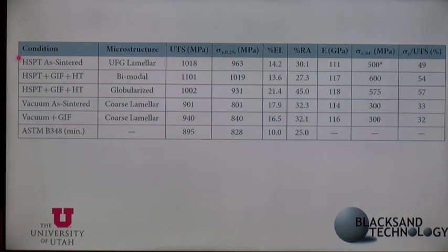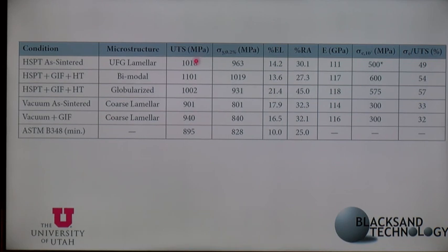Here's a table just showing generally what these things go through. So these specific numbers don't matter. The whole point of this is to show that our material outdoes ASTM standards and vacuum-sintered standards by quite a bit. As you can see here, it exceeds it by about 20, 30%, and at 10 to the 7th cycles, the strength it can sustain is vastly higher than the others.